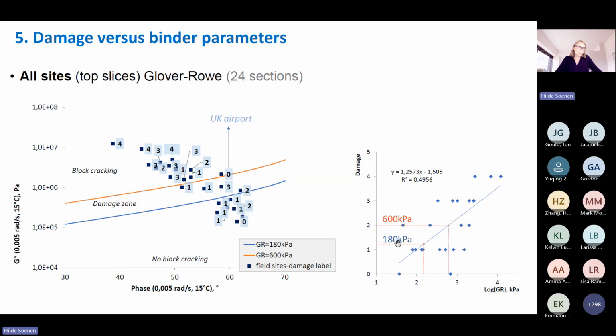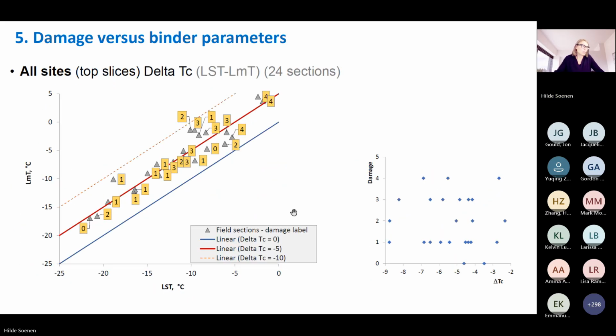And we also see that the proposed limiting levels, so the warning of 180 kilopascal for the Glover-Rowe, ends up close to a level 1 in the damage, and the 600 is the change from 2 to 3, which is, in fact, where you have already some damage and move to the connected levels. We did the same thing for delta TC with all the sections now, and again, there is no correlation that one could see here.